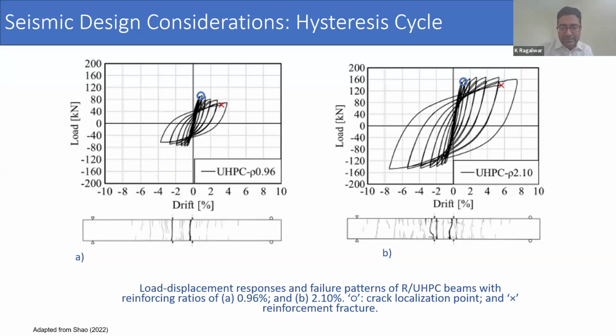This added capacity allows new localized cracks to develop, which distributes the reinforcement plasticity over a larger portion of the beam instead of all the deformation happening in a small zone. The plastic strain spreads out over the beam length, and this results in member ductility. An important trend here is that ductility improves with higher reinforcement ratios.